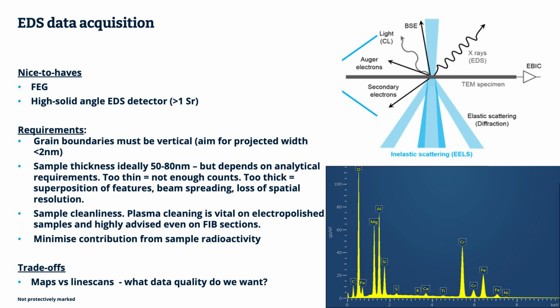Artifacts that you need to be aware of are particularly from sample activity. If you're using an electropolished disc, there's a huge amount of the disc which you're not using but is contributing radioactivity to the background signal that your X-ray detector sees, and that can require some substantial corrections to try and remove artifact peaks. In the case of neutron irradiated samples, it results in a very large manganese, or apparent manganese X-ray peak, which, since it sits right here on the back end of the smaller chromium peak and overlaps with the iron peak, has to be accurately deconvoluted, or attempted to anyway, otherwise the quantification is going to be completely meaningless.